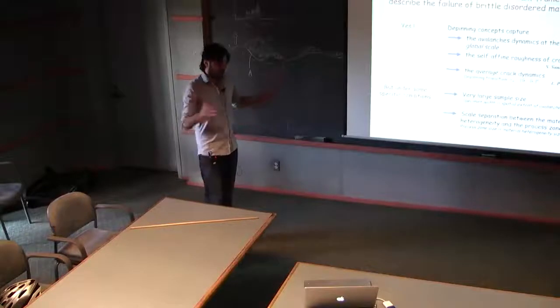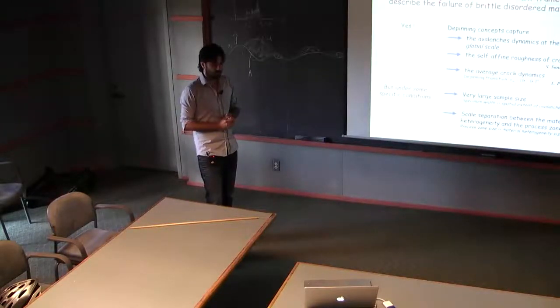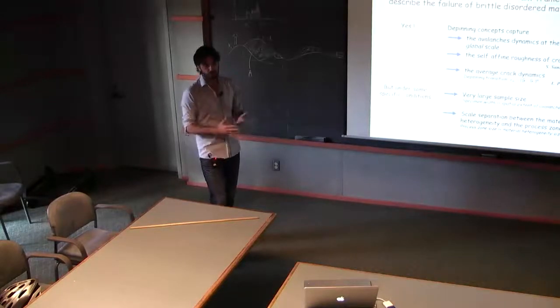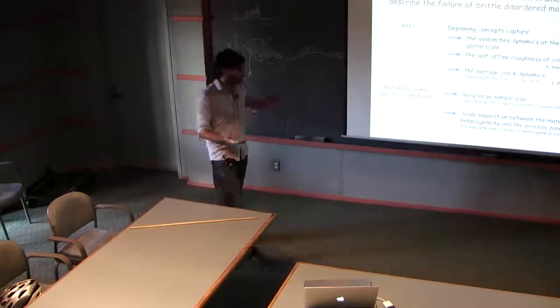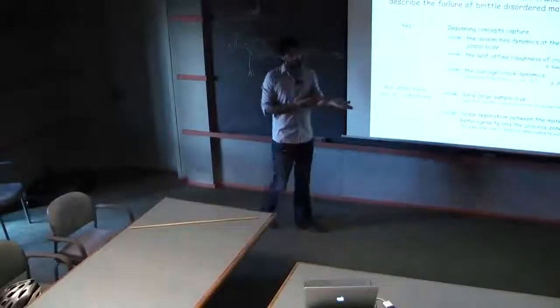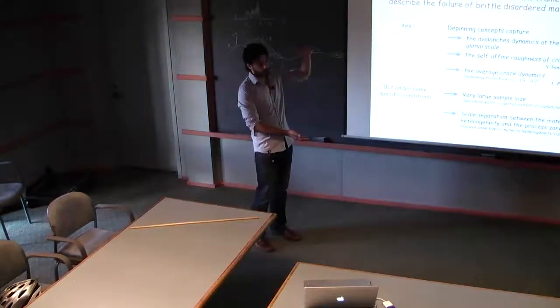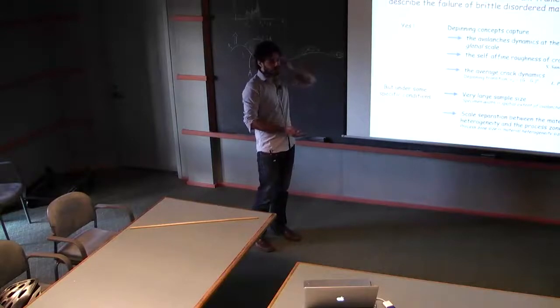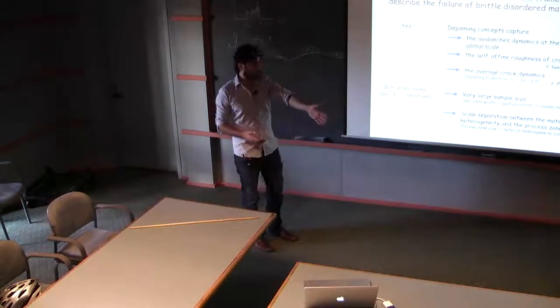The intermittency is macroscopic. It's not a microscopic correction you can smooth out by taking a sufficiently large volume. Yeah, you're driving with this velocity, right? So there is a constant K. So what is K? This setting, K, is going to set a macroscopic length scale due to the loading condition. And generally, it's the crack length, the total crack length or the specimen width. So this is your cutoff. It will set a maximum avalanche size.